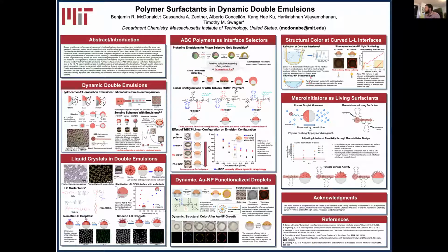And so what we learned is that our gold nanoparticles are scattering light and basically serving as amplifiers of this structural color phenomenon, which arises, like essentially all structural colors, from light being reflected and traveling different distances and then re-interacting with itself, resulting in interference between these rays.